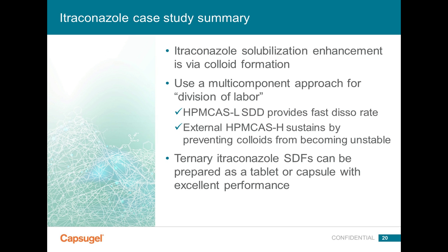To briefly summarize this Itraconazole case study, in general, the problem statement for Itraconazole is that we need to solubilize an ultra-low solubility compound. And the majority of that solubilization is achieved via colloid formation. So we use a multi-component approach to divide the labor using the HPMCAS-L SDD to provide a fast dissolution rate, and external HPMCAS-H is able to help sustain the colloids to prevent them from growing in diameter too quickly and falling out of solution. Ternary Itraconazole solid dosage forms can be prepared as either a tablet or a capsule and have equivalently excellent performance as the SDD powder.